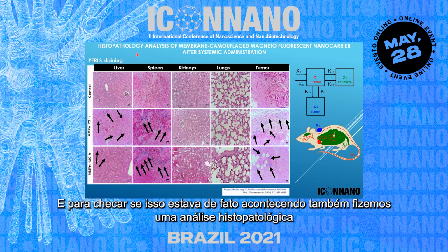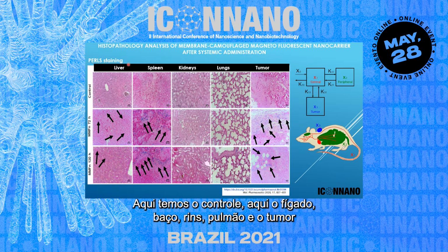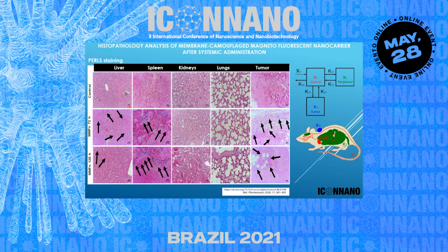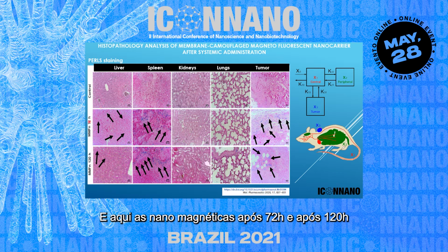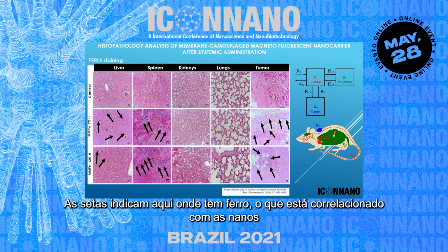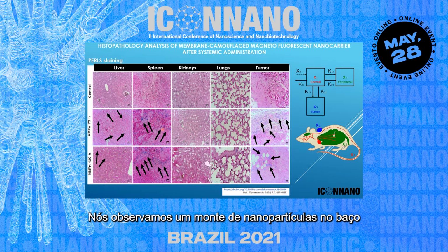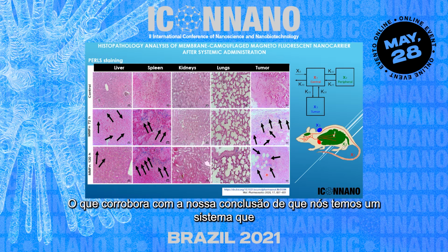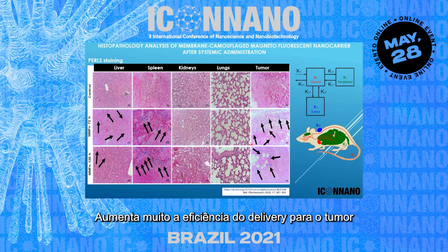And to check if this was really happening, we also did a histopathology analysis, Perls staining. So here you have the control: the liver, the spleen, the kidneys, the lungs, and the tumor. And this is the magnetic nanoparticle at 72 hours, and this is 120 hours. The arrows here indicate in blue where there is iron, and this is correlated with the magnetic nanoparticles. So we do observe a lot of magnetic nanoparticles in the spleen for this type of nanocarrier. We do see a little bit in the liver too, and we see a lot too in the tumor, which corroborates our conclusion that we have a system that increased the delivery efficiency to the tumor a lot.